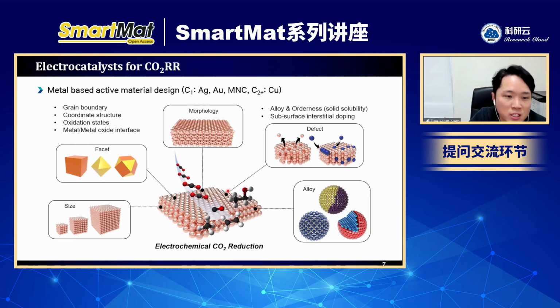Although we make this kind of facet size, morphology, and alloy system, they all undergo reconstruction. And so far, it was very difficult to understand how the surface or the facet changes. It means that although we make an ideal interface which can produce C3 products, it can be degraded or changed in another way. So if we find a way to manage or handle this reconstruction, by maintaining the active sites or inducing reconstruction that is very active for C3 chemical production, that will be the future direction we need to focus on.